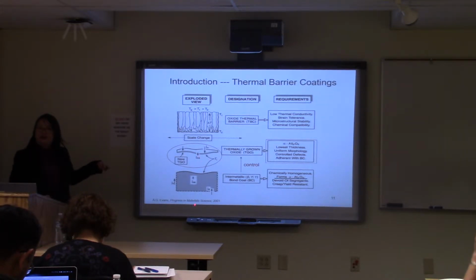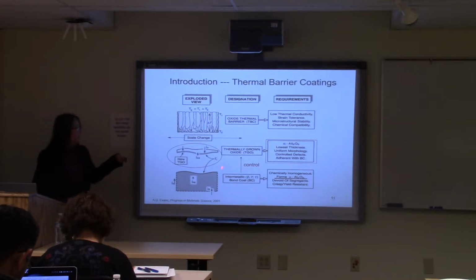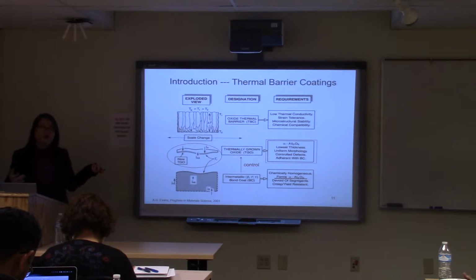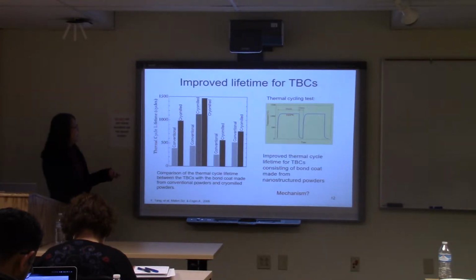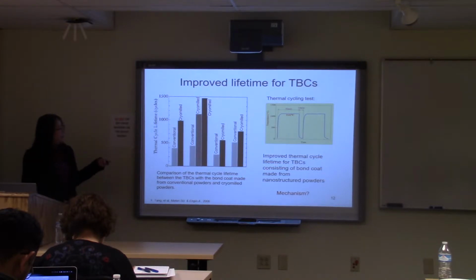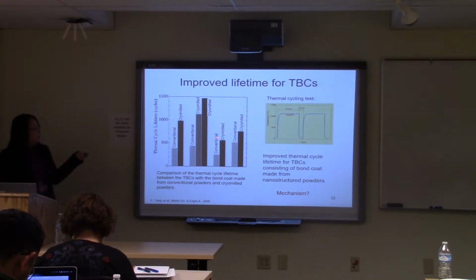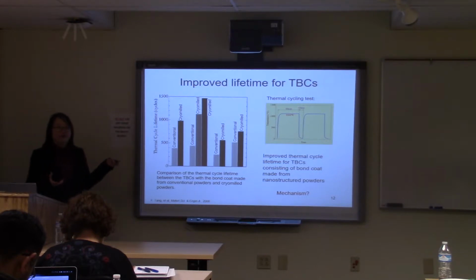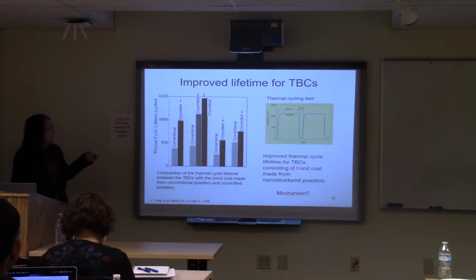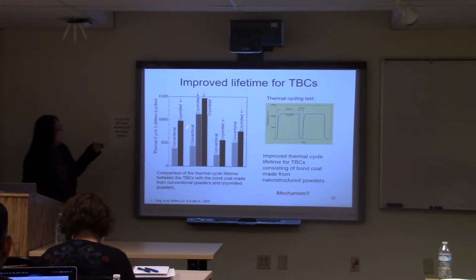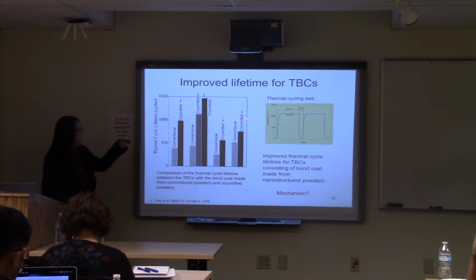Because your aluminum here comes from the bond coat, that's why I'm interested to see whether the nanostructuring of this metallic bond coat can change the oxidation behavior. One of my previous colleagues found that if we develop those thermal barrier coatings using the cryomilled powder, we can get improved thermal cycle lifetime, which I highlight in those bars. The darker bars correspond to the cryomilled material, and the light ones are the conventional.